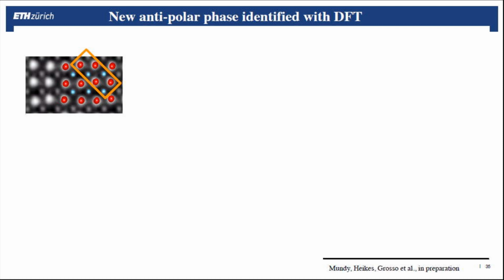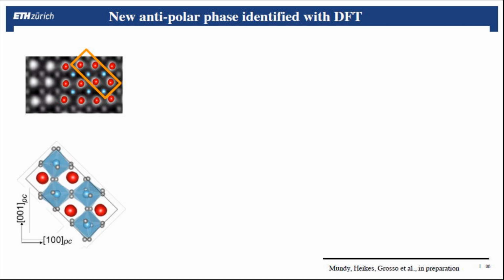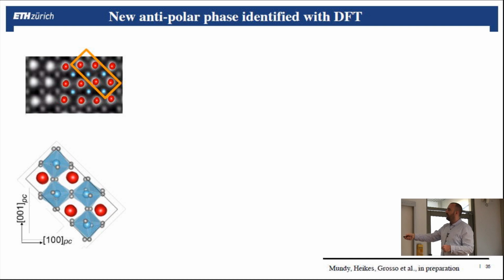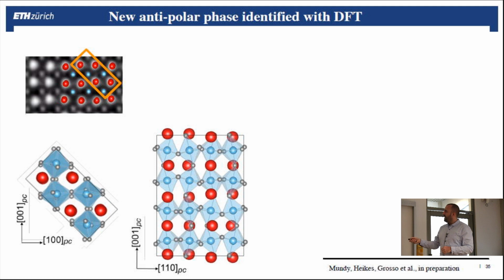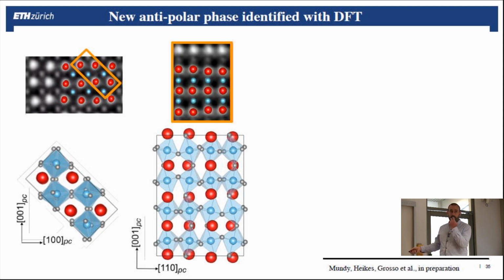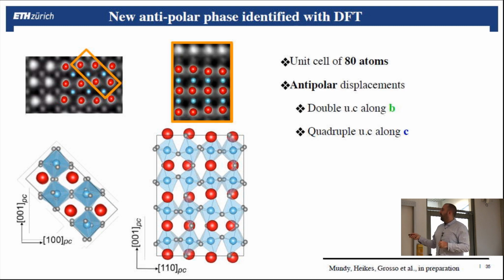So the first distortion that I showed you was the 2 up, 2 down. And I just colored here the unit cell to help you, and this is what we computed theoretically. And you see, maybe it's not easy to see, but it's actually here, these two are moving up, these two are moving down. Now if I rotate this structure so we're seeing something like this, and now I will put it vertical, this is what you get. And you can see here that you have 2 up, 2 down, flat, 2 down, 2 up, flat, 2 up, 2 down, and so on, which corresponds to the other distortion I showed you. This means that this arrangement of atoms corresponds to the one that was experimentally observed. And it also means that these antipolar displacements are also verified theoretically.